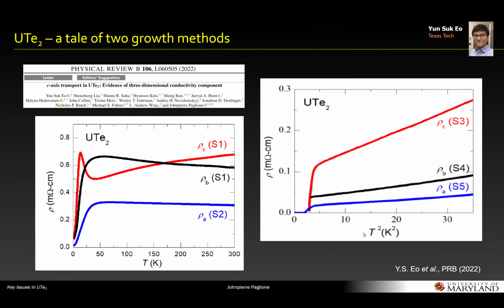You mean this data? Yes, because they're different on the two samples. You didn't explain it. So the question is, why are these different? If I look at the left sample data and the right sample data, it looks different. Oh, I see, you plot it in a different way. This is at low temperatures, just to show that we see T squared in all three directions. But there's a bit of a flip of the order. You see that the A-axis resistivity seems to be lowest at low temperatures. Sorry, B and C kind of flip orders, but that's not a strong statement because B and C show qualitatively different behavior.